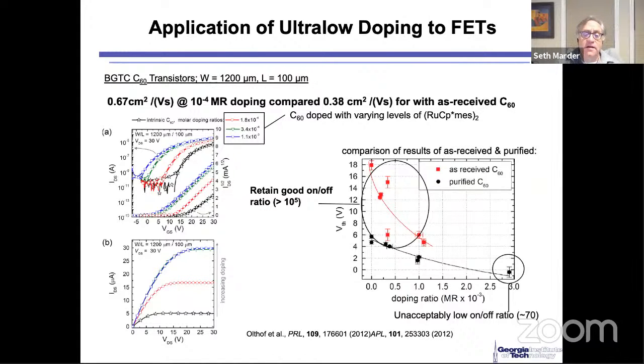Then what they did was they made transistors out of these materials. Now, when you took the pure C60, you ended up with a turn-on voltage of 18 volts. That's the threshold voltage between the gate and the drain. And then if you doped it, what you can see is that, again, at 10 to the minus 3 mole percent, that threshold voltage dropped to about 4 to 5 volts. And that was done retaining a good on-off ratio for the transistor.